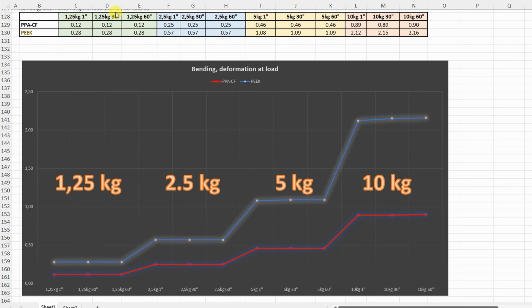The deformation under these loads after 1, 30 and 60 seconds, smaller numbers are better, so PPA-CF is very stiff material here, but the PEEK has more deformation. But look at this, on 10 kg it has very minimal deformation during the time, so not bad results, but yes, compared to the PPA-CF, this is weaker.